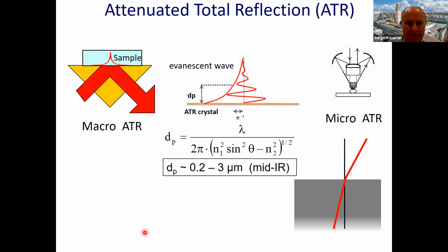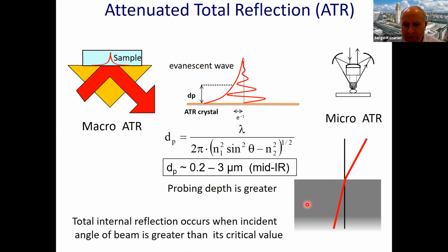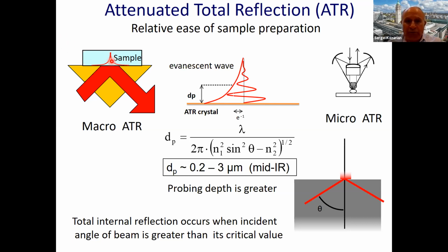So here I show the principle of the ATR approach. It's internal reflection, not external. You have a crystal with high refractive index, typically like zinc selenide or diamond. You place the sample on top, and when certain conditions are met, and I show you here what conditions are met, in this animation on the right-hand side, you can see I increase the incident angle, and only when I reach the critical angle, which is defined by Snell's law, internal reflection occurs. And when it happens, the electric field of light still would penetrate into the sample, but as an evanescent wave. It would be decaying exponentially, and when it decays by a factor of e, it's called depth of penetration. Of course, probing depth is greater, but it allows you to measure samples relatively easily if you get good contact, up to a several micrometer layer within this sample.